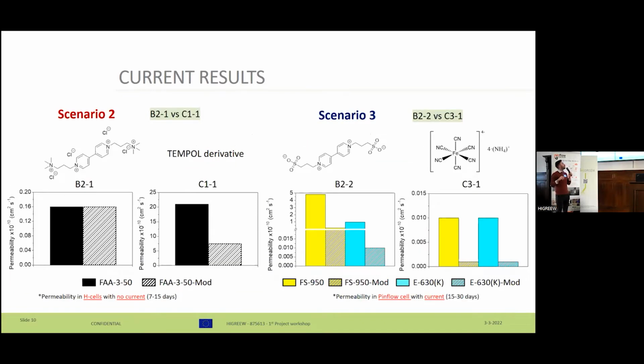Also, HIGREEW was dealing with another 2 different scenarios. The scenario 2, which is considering the B21 and C11 molecules, as you can see. And again, the modification proposed reduced in most of cases the permeation. And in the scenario 2, I have to say that based on the chemistry involved, we needed to use anion exchange membranes. Whereas in the scenario 3, according to the B22 and C31 molecules, the family of membranes that were required to evaluate were cationic ones. And also, as you can see, the permeation rate was reduced when using the modification.